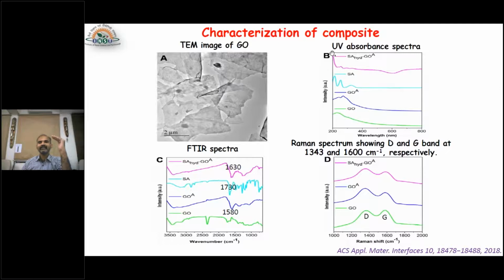So next, here in the carbon also there is a good optical property, and it gives an absorbance at 280 nanometers. Okay, and then when you are conjugating with amine, it gets shifted. Okay, and then when you are conjugating with the next one, we are following this all sequentially till the salicylic acid binding. Okay, once it is bound with salicylic acid, you get the strong absorbance as it is here at 320 nanometers absorbance for the composite. And then the same optical spectra, that is FTIR spectra, can be used to visualize each and every functional group on the material.